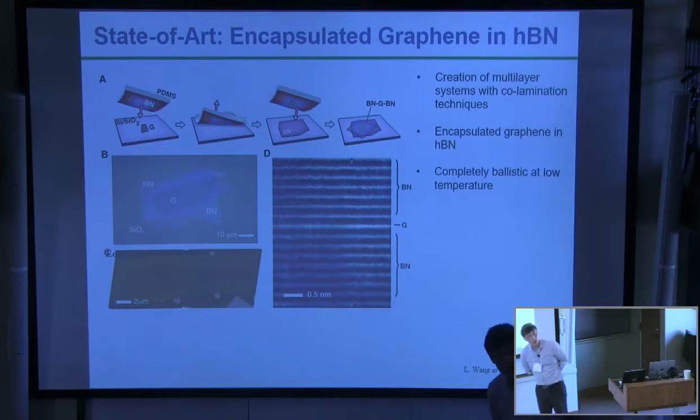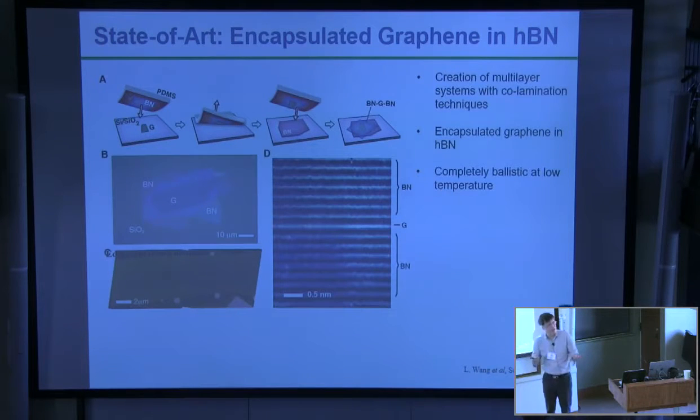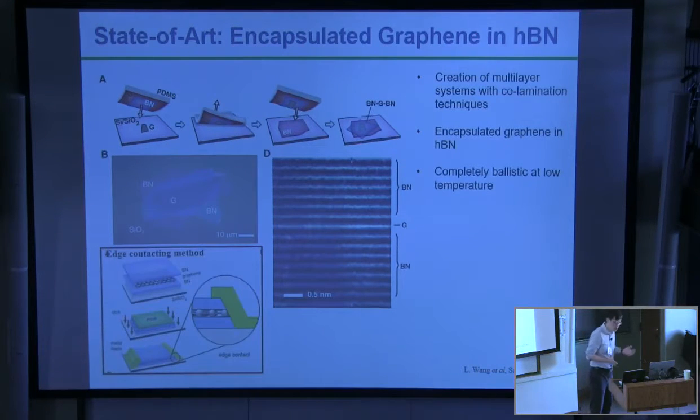Thanks to the technique called boron nitride encapsulation, one can mimic making quantum heterostructures using graphene and boron nitride. It's like the MBE-grown samples, except that it was assembled by hand. But nevertheless, the technique has been perfected such that you can create an extremely clean interface, where graphene is encapsulated between the boron nitride, and then make the device out of it.